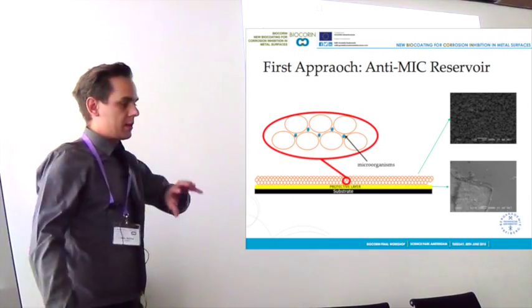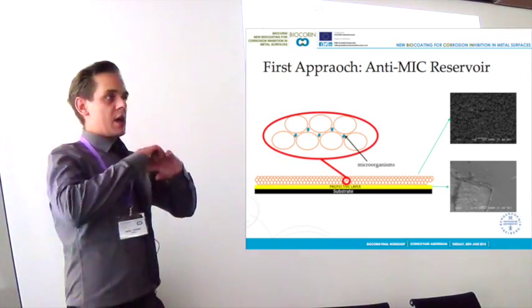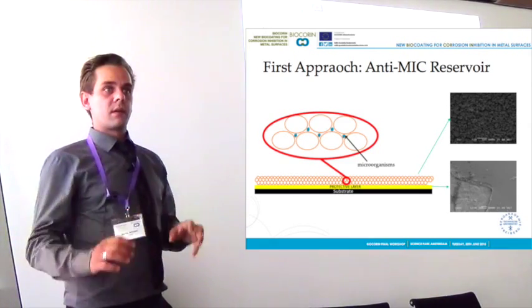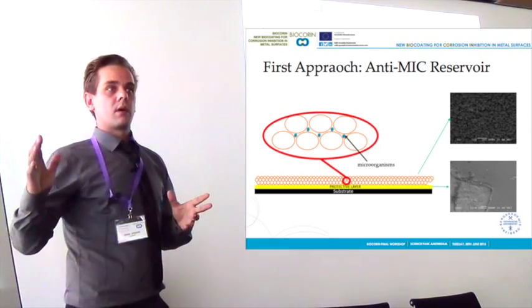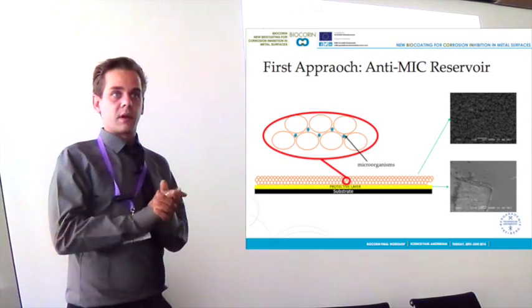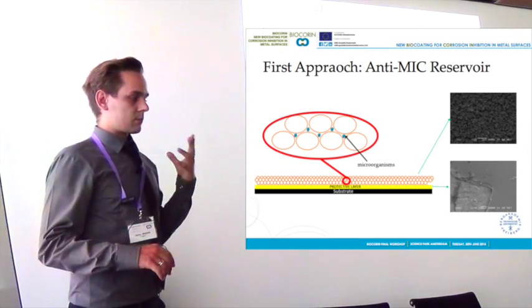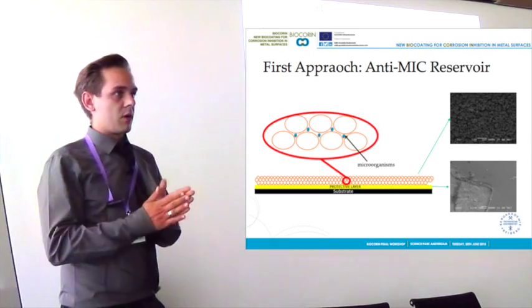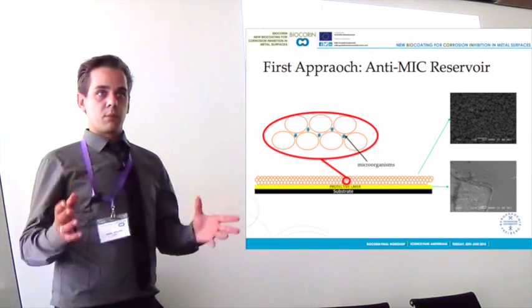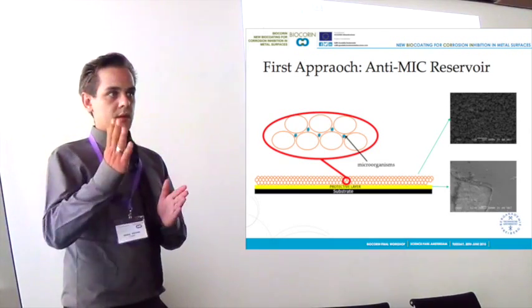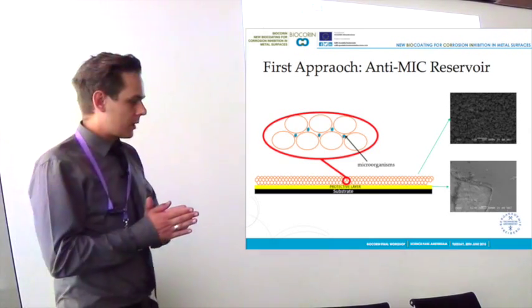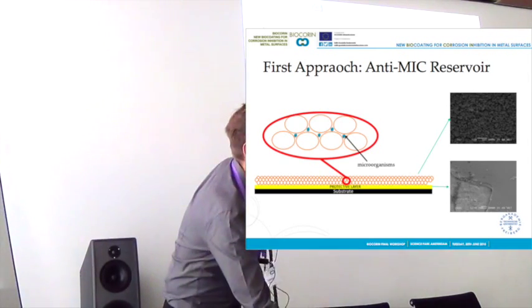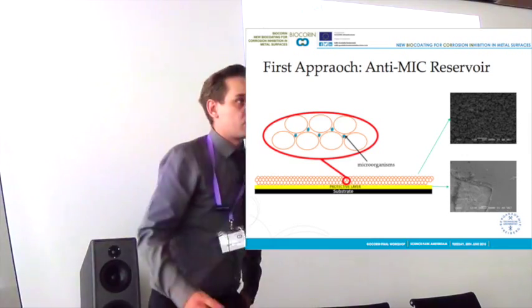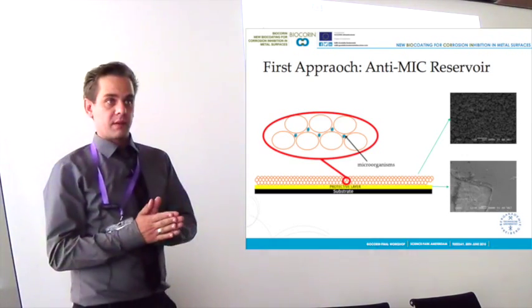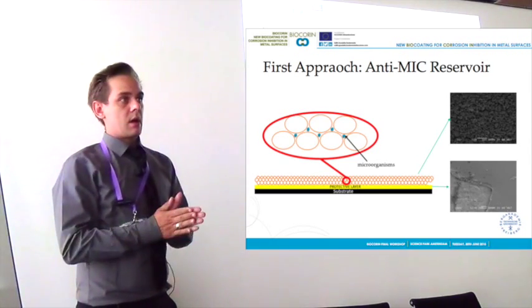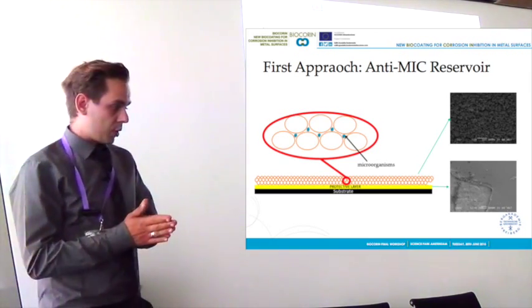The idea behind the porous coating was that a high amount of the microorganisms can be integrated into the porous system. Nutrients can go into the coating, and that should ensure that the microorganisms that are integrated are viable and can produce the anti-mic components. Both systems you see here in the same image. The protective coating was very promising and showed good results. A very dense coating with high protection properties, corrosion protective properties.